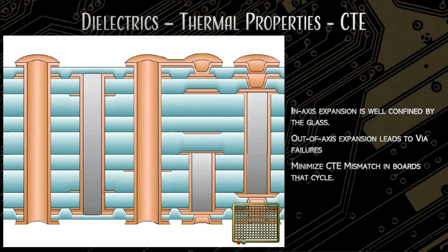So what's really happening is the fiberglass is trying to make the board expand, the copper is trying to pull it back together, and if you let that happen over time, you end up with via cracks, barrel cracks, and separations at the plating where these things join. You end up with all sorts of different types of failures, from open circuits to high resistance shorts to, I mean, fire. We don't want fire, but it could conceivably happen. So you want a material that is reasonably well matched from the CTE standpoint to that of copper. Is that ever a concern when you're designing a board, Teresa?